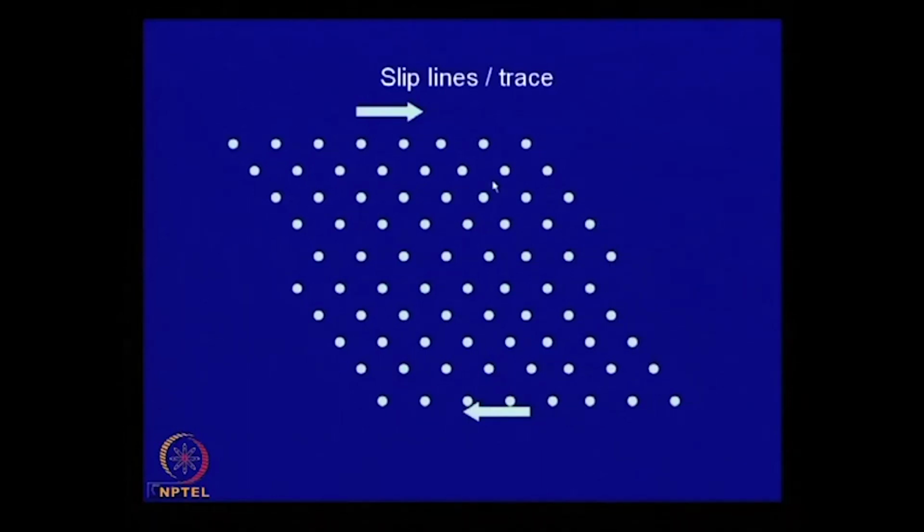But normally, to look at a microstructure, you polish, grind off the surface, make it smooth, then you etch it with a chemical agent. Since the orientations are identical, if you grind off, this portion goes, and there is no trace left behind. So if you look at this microstructure, both sides of the slip plane will look identical, and you will not be able to distinguish them.